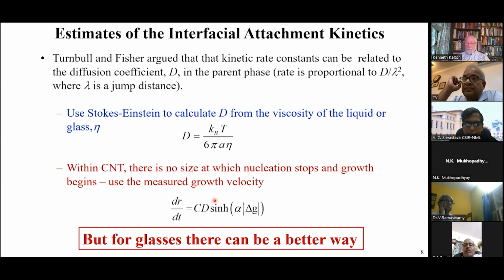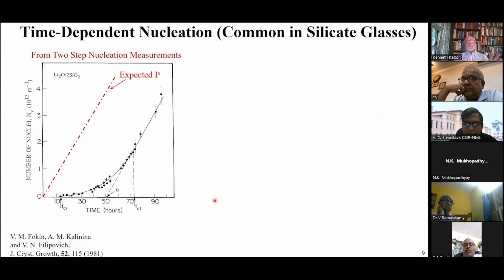And this was first developed for silicate glasses. So let me talk a little bit about silicate glasses. Silicate glasses, it's a very big industry, both for the glass as well as for the glass ceramics that you make from the silicate glasses by controlled heat treatments. Since you want to make a desired microstructure, you need to know the nucleation rate and the growth rate. So places like Corning spend huge amounts of effort to try to measure this.